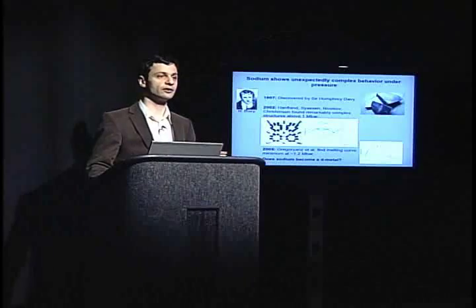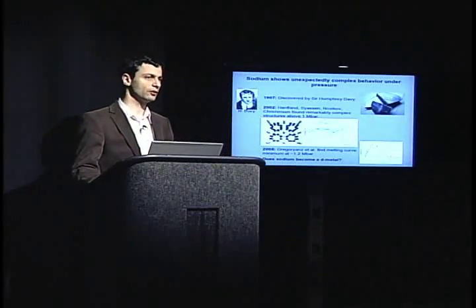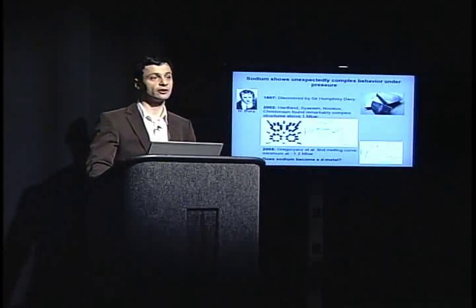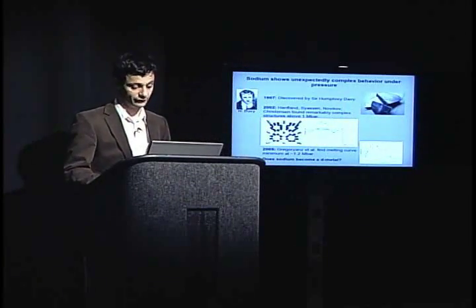Theoretical calculations and this number of unusual experimental observations suggest that sodium indeed might become a d metal, if you like, a transition metal under pressure, dramatically changing its chemistry from a simple, nice, white, silvery metal to something which behaves very differently.